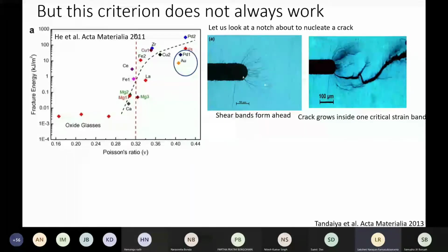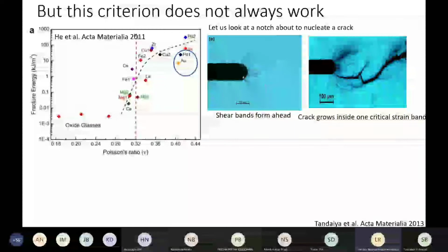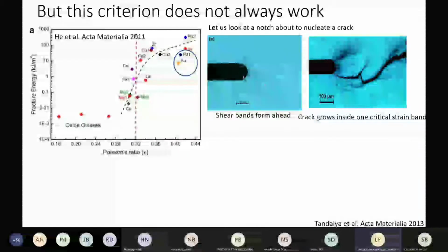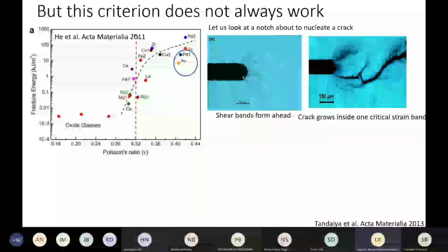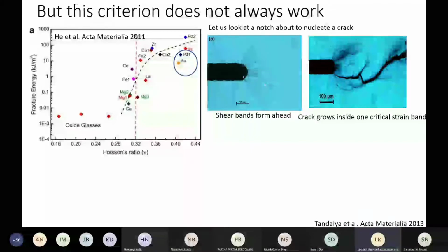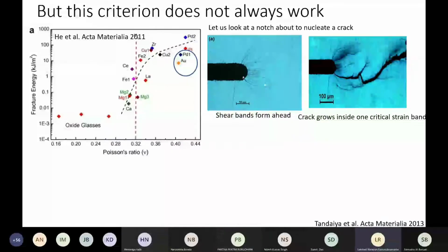And what happens is when a crack really nucleates, it forms within one of these shear bands. And that is very evident here. You can see on the left, this is just before when a crack forms, and on the right, a crack actually goes through one of these shear bands. Not all of these shear bands are cracks. They can be potential cracks, but only one of them is chosen to be the vehicle for the crack to propagate.